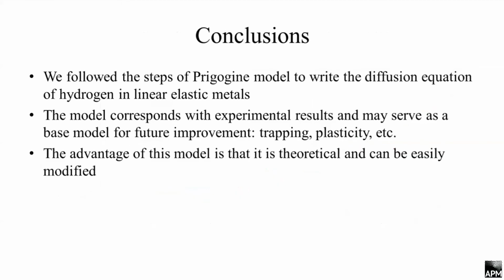So actually that's it. We followed the steps of the Prigogine model to write the diffusion equation of hydrogen, and of course we obtained something more or less corresponding with our experimental results, and we checked the advantage of the possibility of this model, because now we can add some rating based on chemical activity and so on. We can add plasticity, some changes in constant parameters of the material, and the great advantage of this model is that we didn't restrict ourselves with some parameters and so on. So it's our hope that the model is theoretical and can be easily modified if it's needed. So thank you for attention.